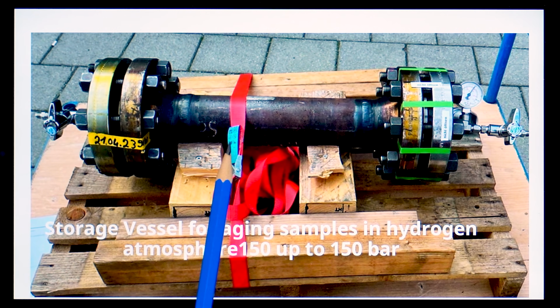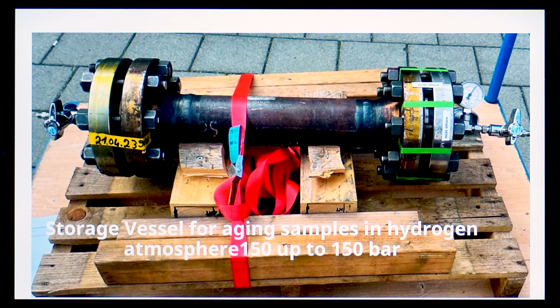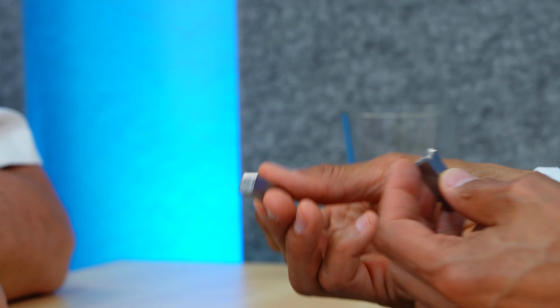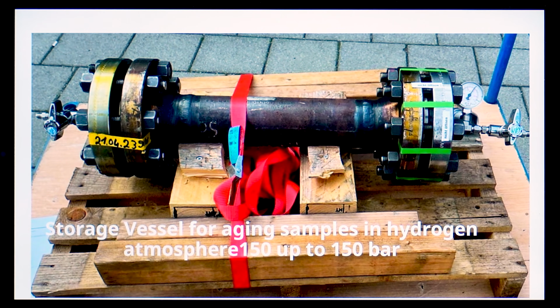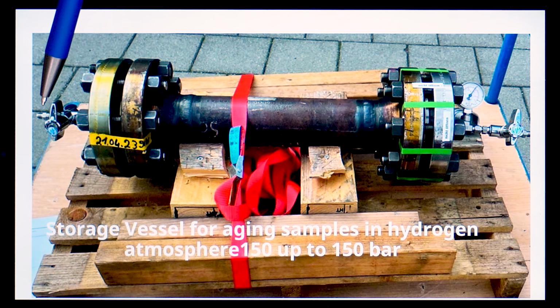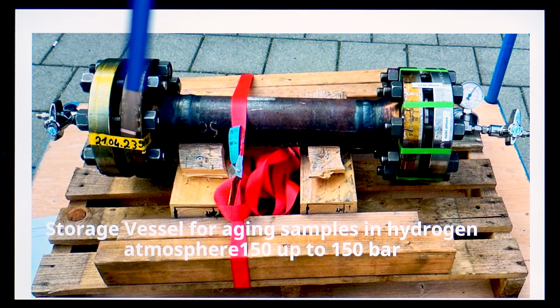Okay. And we also have larger chambers where we can put complete components inside. Either we fill the components with hydrogen, or we fill the outside, so that the components are aged under hydrogen atmosphere. Okay. So basically, this one would have been inside there. You push the hydrogen gas inside, and then you close it up and you write the date on. Yeah, and then we wait maybe 50 days, and then we take them out. And then you do the test. Then we do the test, and we compare non-aged samples with aged samples, so that we can see, is there a difference?